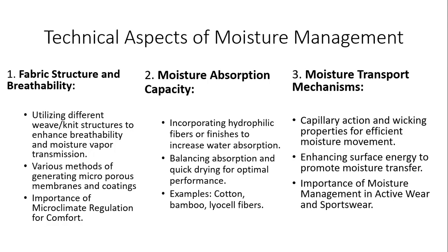When it gets in contact with a surface, most of the time these water droplets get spread. Why is that? It is because the surface in touch with the water molecules does have high surface energy. So when it has high surface energy, the water molecules tend to get spread. Spreading is done through changes in the surface energy. So why does the lotus leaf bead water? It is because it has a naturally engineered structure where the surface of the lotus leaf has comparatively lower surface energy compared with that of the water molecule. So therefore the water stays like a bead.